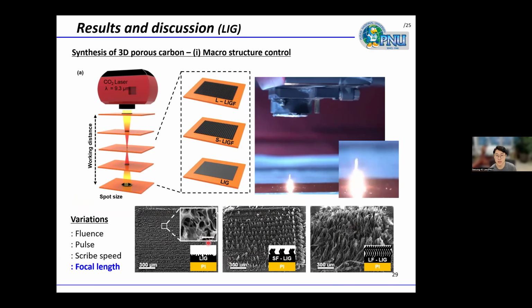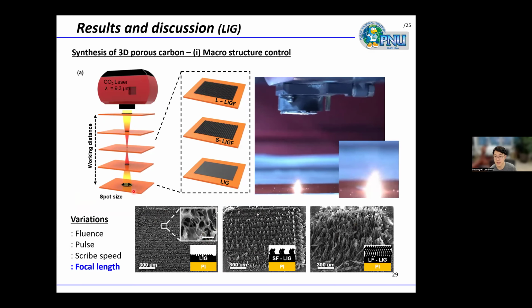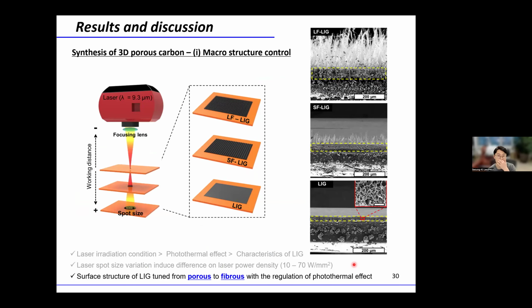As shown in here, using this kind of defocusing method, we can control the structure of LIG from these porous structures to the fibrous structure. As shown in this cross-sectional image, the fiber-shaped LIG exhibits a length exceeding 300 micrometers, and this can be controlled by a simple parameter, that is, the focal length of the laser.